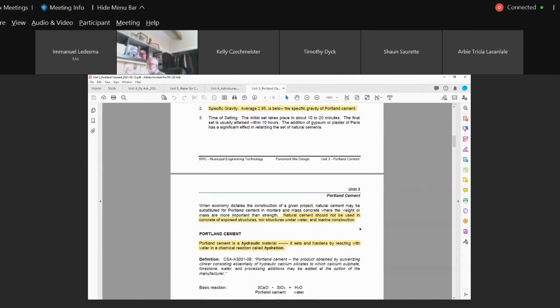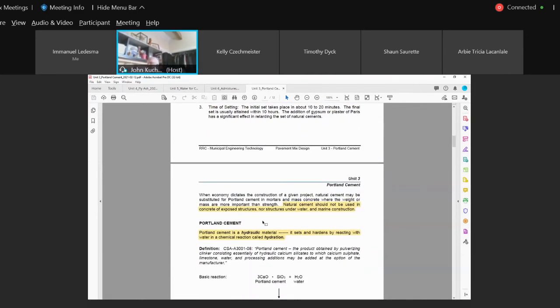Again, natural cement should not be used exposed to structures, water, marine environments—not resistant to salt attack as much as our normal Portlands, because we can manufacture and change the composition of ingredients in various cements. That's why we have 6 types of cement—in Canada we have 6 various types. By changing raw materials, we can change the composition of the cement, make one more resistant to sulfate attack, or make one produce less heat of hydration, in other words not producing as much heat.